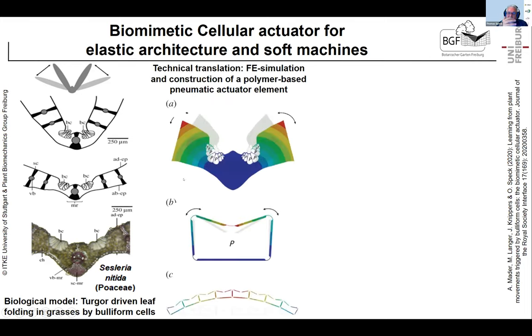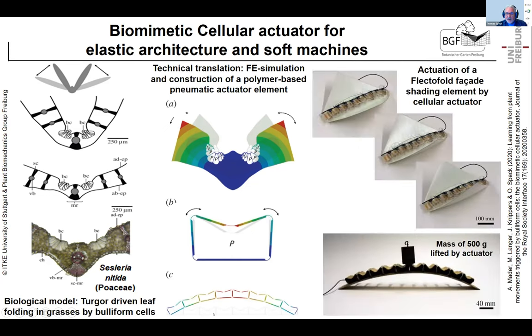And this was done again in collaboration with our colleagues from Stuttgart with an FEM analysis, and we made a very simple 3D printed model. We have stiff walls here, and flexible walls at the hinges, at the center, and here. If you inflate them, the side walls go to the outside and the upper wall goes up, exactly like in the bulliform cells. If you combine several of these elements and inflate them, they bend up, and if you deflate them, they go down. With this, we had a cellular actuator for our flectofold.